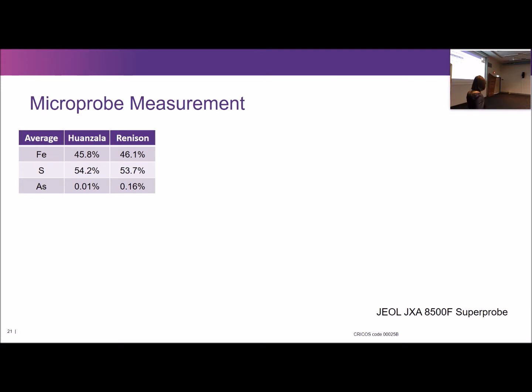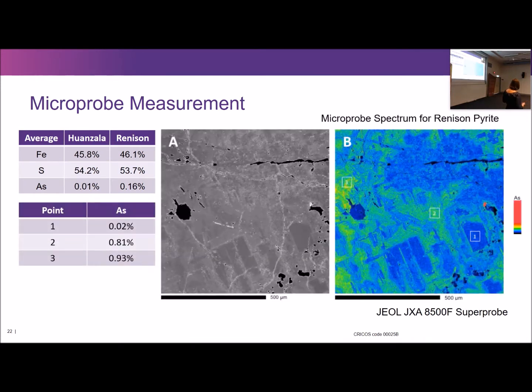And first, the iron measurements for the two were very similar, slightly more in the Renison pyrite, same with the sulfur, but the Renison pyrite contains 0.16% arsenic, whereas the Huanzala pyrite contains 0.01% arsenic. It's a tenfold difference, but they're all very, very small, so can this really be significant? Well, if you look at what the surface actually looks like, this is Renison pyrite.